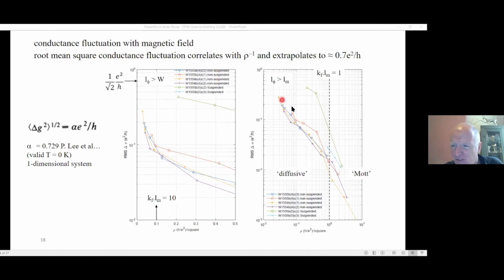Now this is data over about 3 orders of magnitude. It's a power law to the -1, which is just the conductivity. So the root mean square conductance fluctuation just depends on the conductivity. There's 2 regions here. There's this Mott variable range hopping region and the diffusive, diffusive metallic region. So k_F l_m is the product of the Fermi wave vector and the mean free path. That's about 1 between the 2 regions. The device doesn't really see that. Now, to see these conductance fluctuations, the phase coherence length has to be larger than the mean free path,